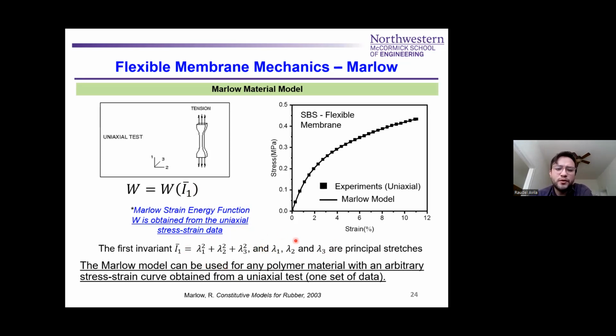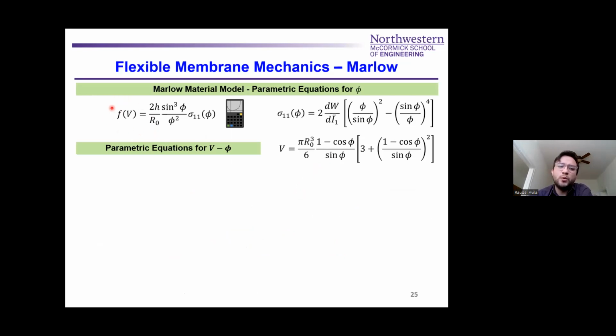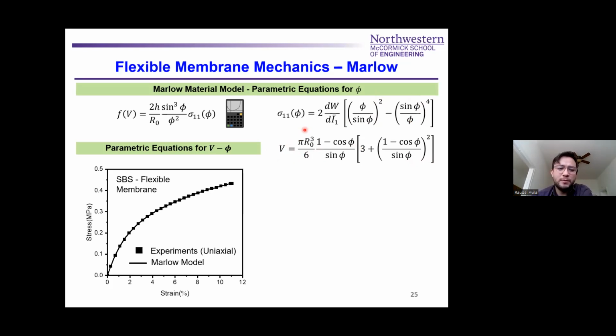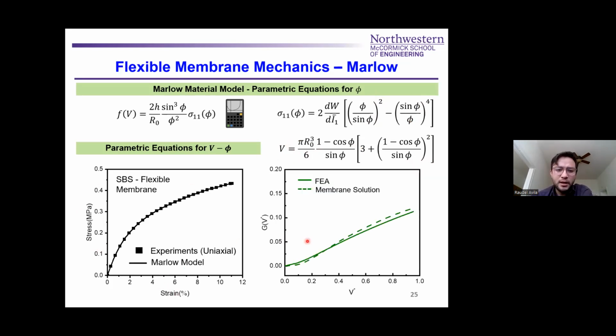And you can use this for sort of any polymer material that you want to fit into your hyperelastic law. So this is more interesting if you have a material and you can fit its mechanical deformation, then you can also find what the function f(V) is going to be, and you build it directly from your material data. So here you can calculate what the stress is going to be. This is given by 2 over, you have the derivative of your strain function with respect to the first invariant, and then you have a function of the angle phi. And then you have your volume, which is also given by the angle phi, and you can plot them together. So if you have your stress versus strain, then you'll find what your pressure versus volume function is going to be, analytically, based on the experimental data that you have.